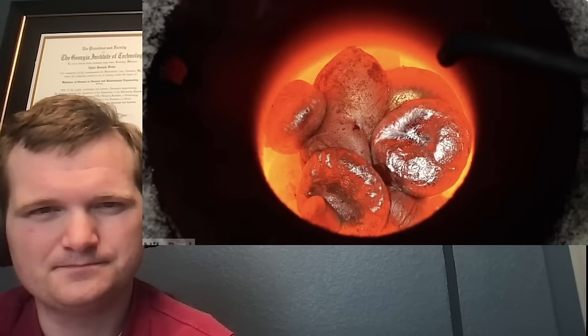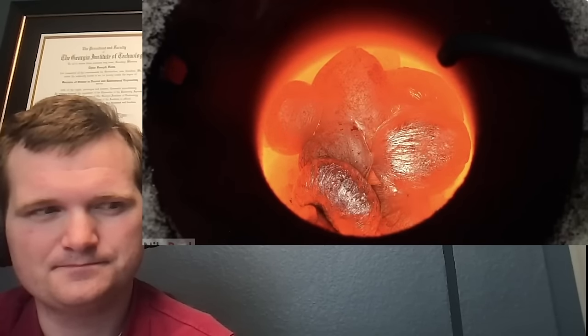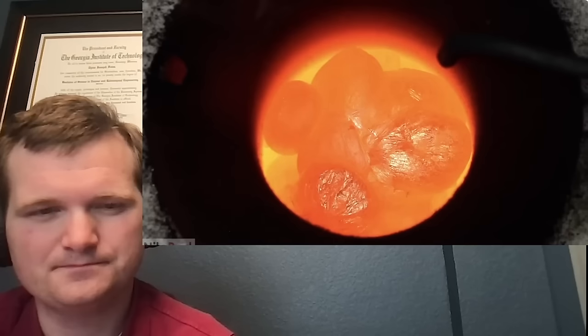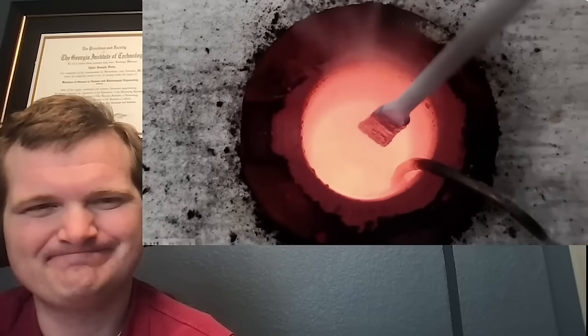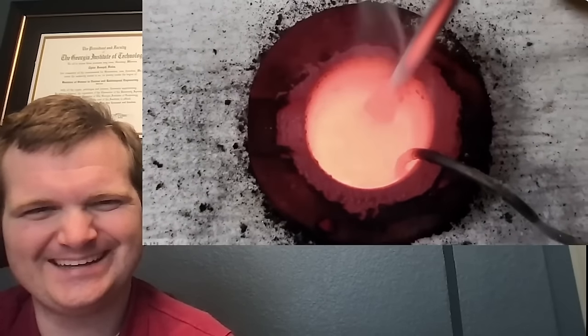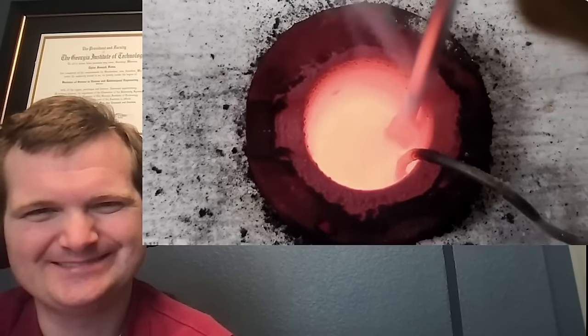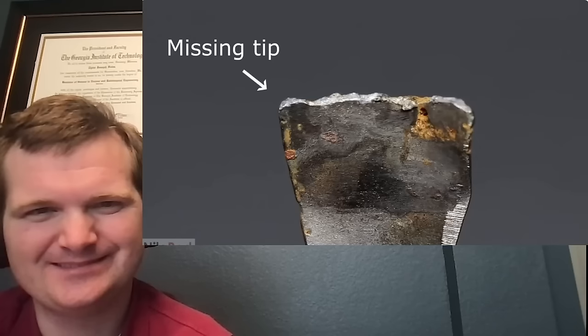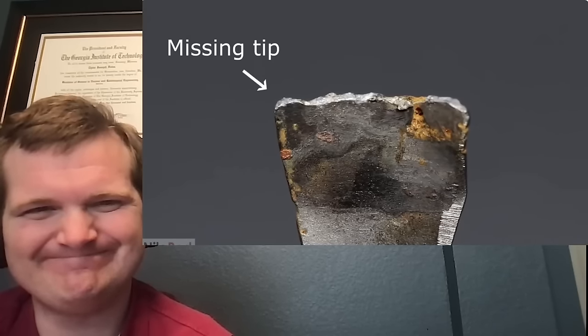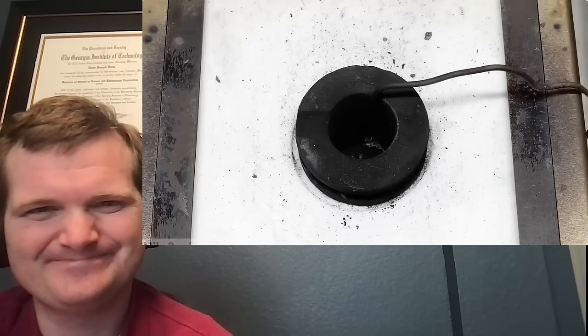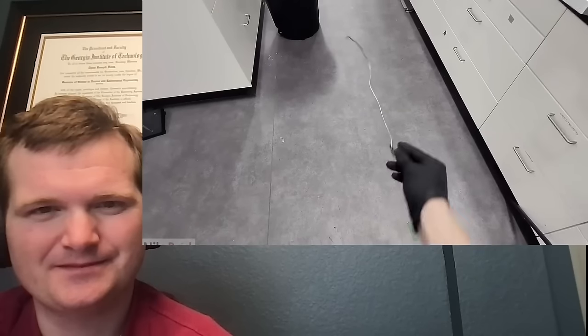This was actually something that I'd been kind of avoiding, because even though it sounded relatively simple, it was kind of tricky, and I wasn't going to be able to just lower in my stainless steel tube. This is because at 1200 C, the aluminum was way too angry and it would just dissolve. I saw this happen firsthand when it dissolved one of my steel spatulas. So I was going to have to swap out my tubing for one with a different material.